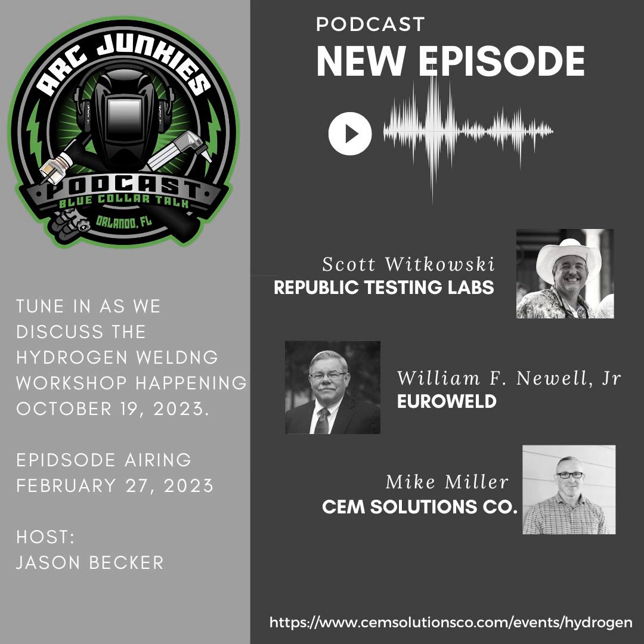Now, Scotty made the comment about welding. When he first approached me on this, I said, well, quite frankly, I'm not sure what to do, but I think I would digress and think about sour service, where we don't want a hard weld. We want a soft weld, if you will, but yet have enough strength and ductility for the service. And then the more I read about this and try to get learned on it, yeah, it's going to be welding exactly like we do sour service, because we need the same result. However, I think we actually are going to need a little bit higher quality weld, especially in the root area, just because of the hydrogen embrittlement. Yeah, you get to use a low hydrogen process to put that root in. Yes. Such as gas tungsten arc welding or gas metal arc welding, or orbital TIG or tip TIG, or some process along those lines. Yes, that's true.